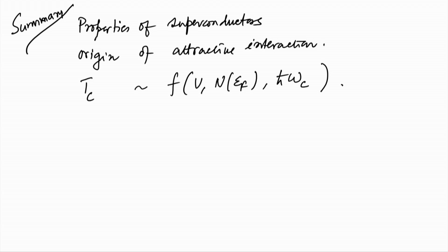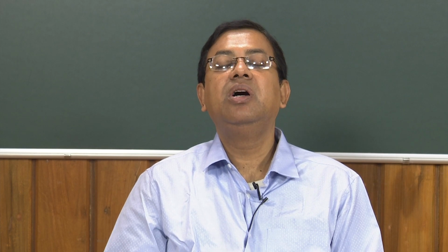And so, you can destroy superconductivity either by using temperature or thermal effects, or by applying a magnetic field, and the state goes on to a normal state, a metallic state, which is apparently not the case for the high temperature superconductors, and they have many other complications.